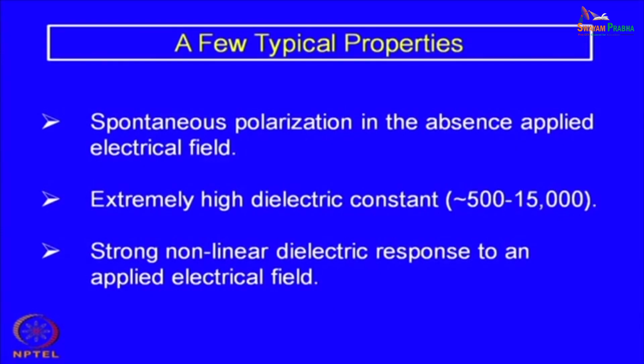Then they have extremely high dielectric constants. All the ferroelectric materials, that is one of their major characteristics, have a very high dielectric constant compared to any other linear dielectrics. One can make use of them for miniaturization purposes, so that a capacitor can be very thin and tiny. The dielectric constant here has been listed as 500 to 15,000, but under certain circumstances it can be further increased to 30,000, 40,000, and in very special circumstances it can go up to more than 50,000.